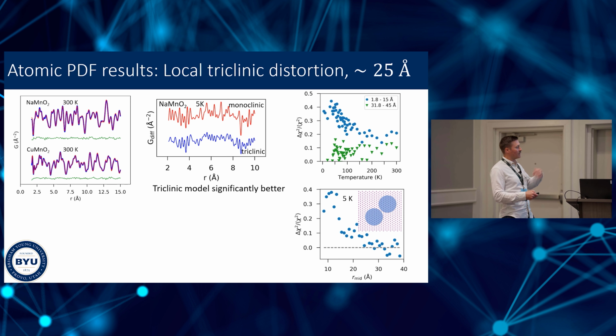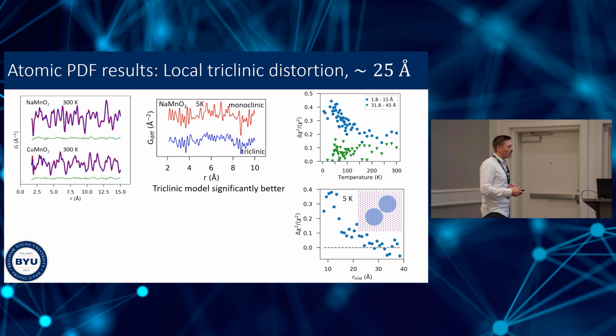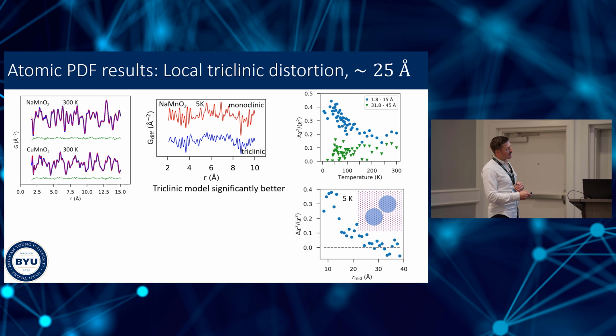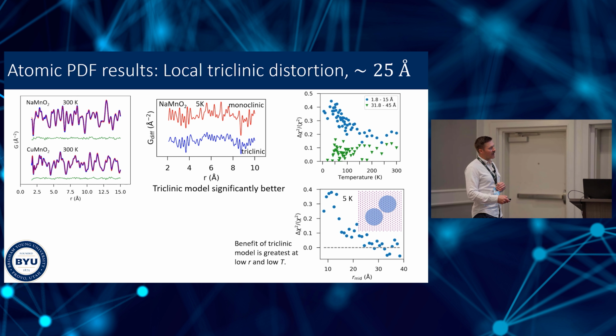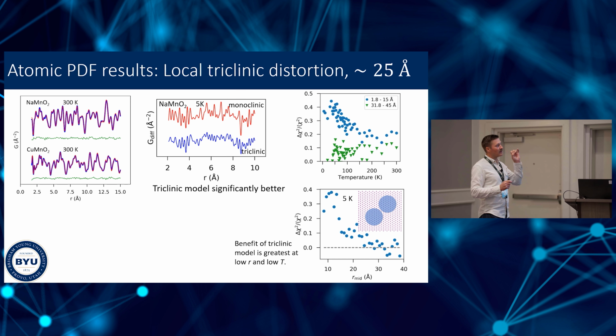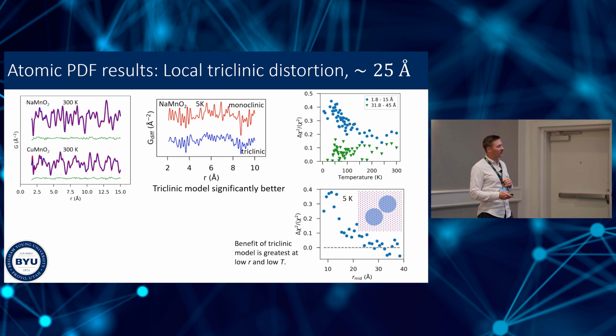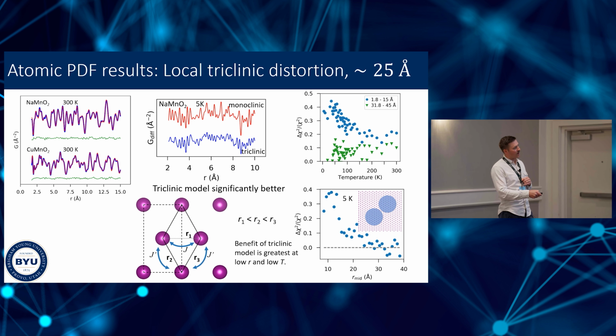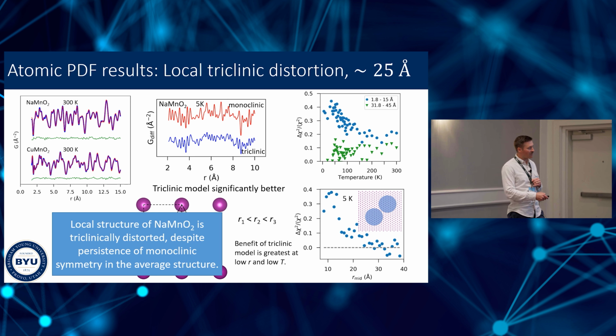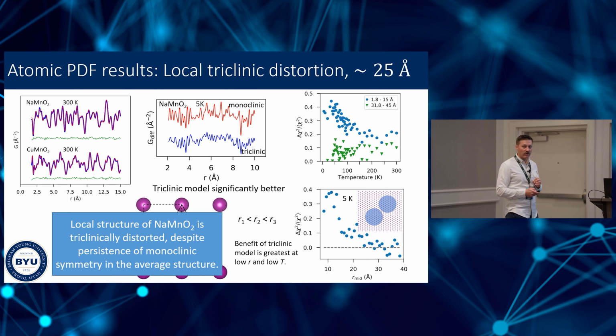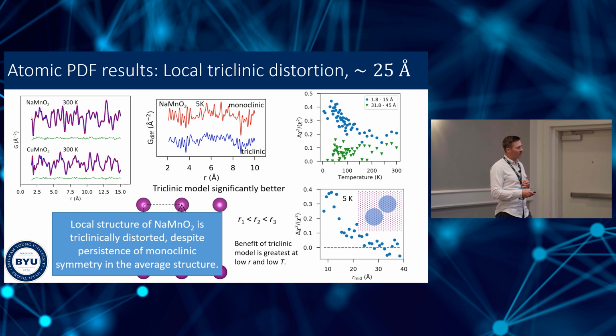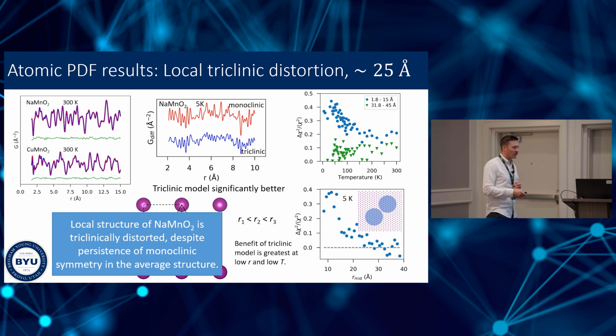Okay, and we can compare the goodness of fit between the triclinic model and the monoclinic model. These details are not so important, but the point is, the PDF data indicate that there is a preference for local triclinic distortions on a length scale of about 25 angstroms that grows below about 150 Kelvin. So at low temperature and short length scales, the local structure of sodium manganese oxide is triclinic. And this is significant because the triclinic distortion results in all three of these triangular legs now being different from each other. So we have fully lifted the degeneracy of these magnetic interactions, and that should allow magnetic order to develop. But to really pin that down, let's look at the magnetic correlations, so magnetic PDF analysis.